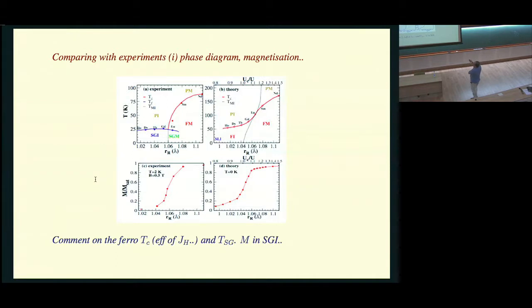Now you can ask, a factor of 2 hardly is a wonderful match. It turns out that when you use a Hund's coupling of infinity, it increases the kinetic energy in the problem, in contrast to the Hund's coupling, which is really 4 or 5 in the real material. So if you could do a 2 orbital 2 spin calculation rather than a 2 orbital 1 spin calculation, you would actually push this down by 40% to 50%. It's a more tedious calculation, but the qualitative physics is the same, and a proper choice of Hund's coupling and the parameters used here probably will give you transition scales which are also consistent with the experiments.